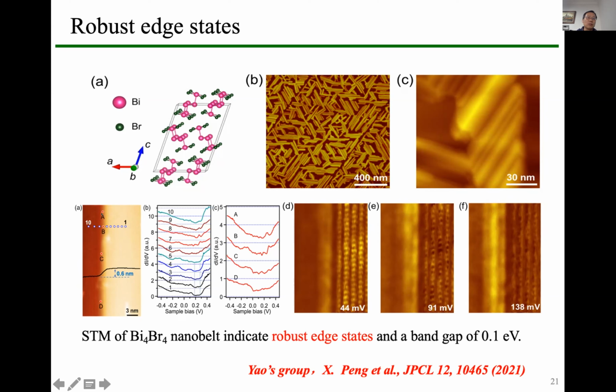And if we take a dI/dV spectrum at different positions along this step edge, then we find that the density of states are rather similar. The dI/dV mapping also shows that they have a one-dimensional feature. So this means these states are topologically protected edge states.